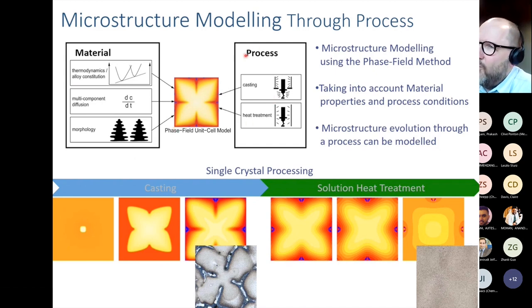But we can now couple this to process modeling as well. So we can get, for example, temperature time profiles coming out of a casting simulation and temperature time profiles coming out of heat treatment simulations. Process modeling is something that's fairly well developed, but we can feed this into our phase field model and then predict the microstructure evolution under realistic conditions within